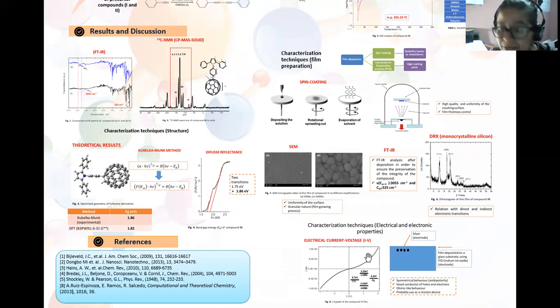Finally, the film was evaluated in terms of its electrical behavior. To carry out measurements of electrical current-voltage, the IV graph, the film was deposited on a glass substrate using ITO and silver as electrodes. According to the IV graph, the film exhibits symmetrical behavior because of the ambipolarity. This ohmic behavior and the value of the band gap are an indication of the semiconductor character of this compound, demonstrating the possibility of using it in optoelectronic devices.